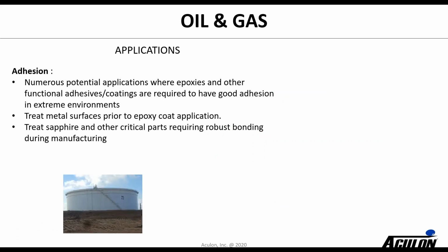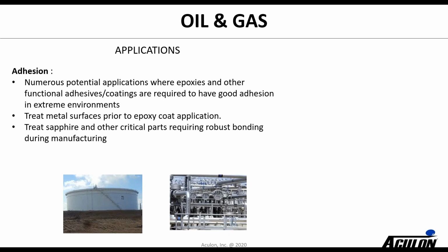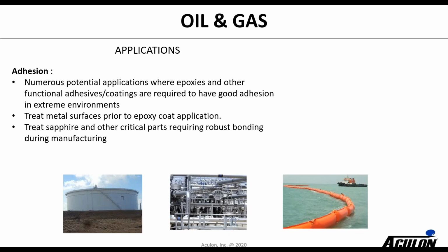So in oil and gas, we've also had some success. There are some pretty extreme environments in the oil and gas space. Down well can be very hot, very humid, so adhesion can be very important. We've been able to help improve epoxy adhesion for a number of applications. Also, being able to treat sapphire and get good adhesion has been important. We've done quite a bit of work in terms of functionalizing oil containment booms, pipes, float sensors, or different substrates that get into a relatively aggressive environment.